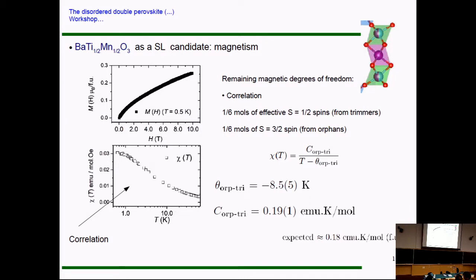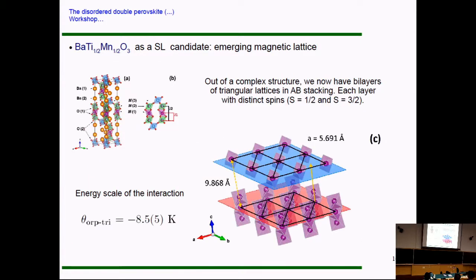So we get an energy scale for the interaction of minus 8.5, and we get a population of orphan trimers of about 0.19 as expressed by the Curie constant here. This should be compared with this number, which is the number expected if you're right, if you simply count and calculate the effective spin. So the idea is, phenomenologically, qualitatively correct. So we will take this as the effective degrees of freedom that we have.